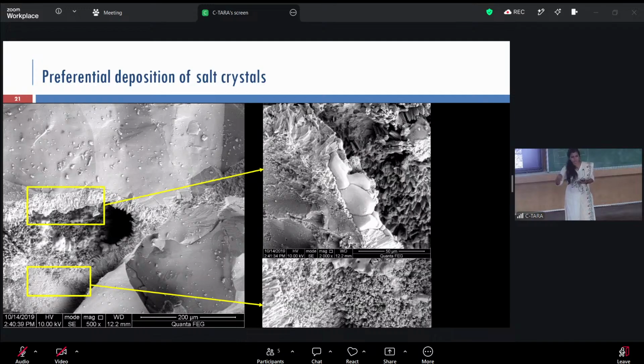These are salt crystals. Salt crystals are going and depositing in this flowery shaped magnesian calcite region only, and not the small crystals. So if a salt is precipitating in larger pores where there is space, it will not damage the material. So we said that, okay, this material will not get affected by salt weathering at this place. This is having good resistance. So then they looked out for other reasons. So then we figured out that it was wind plus seepage, etc.